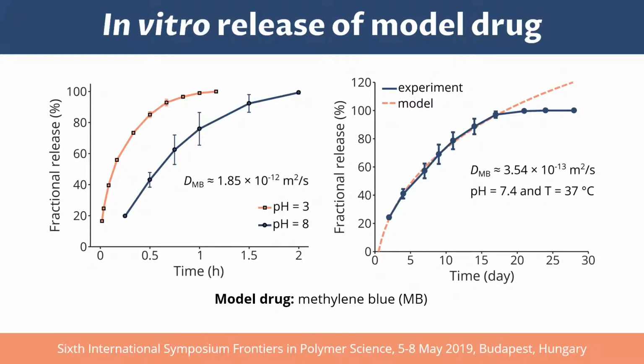We investigated the kinetics of in vitro release from the membranes and implants using methylene blue as the model drug. Example of release kinetics for membranes is shown on the left. The kinetics is obviously pH dependent. At low pH, the carboxyl groups of the hydrogel are protonated. Membrane deswelling occurs and the release is faster than at pH 8. At pH 8, the electrostatic interaction with negatively charged deprotonated carboxyl groups slows down the release of drug cations.